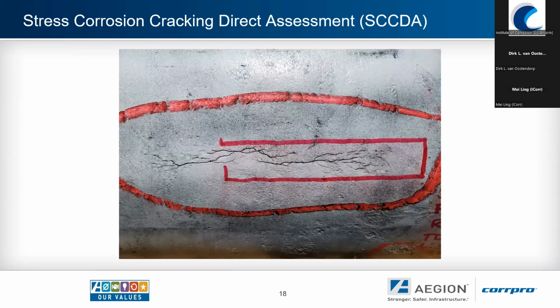SCCDA rather gave us an area that was prone to it. Using a couple of the techniques, we found a specific coating anomaly where the potentials were low. The soil was rather alkaline, and when it was excavated and cleaned, the crack colony, we didn't even need NDT at that point to prove it out because it's pretty apparent.